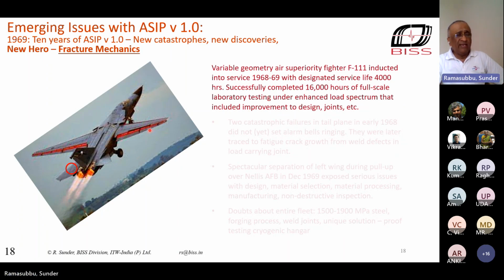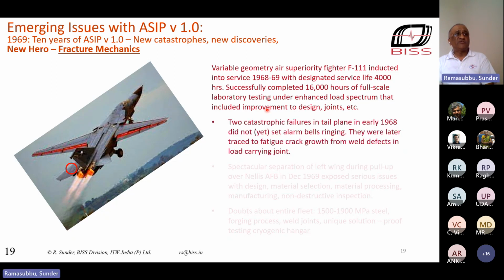So in accordance with the ASIP version 1, it was full-scale fatigue tested. It showed a life of 16,000 hours. They divided it by 4 and said, okay, you can use it for 4,000 hours. Now, very early in service, there were 2 catastrophic failures in the tailplane. But unfortunately, they didn't set alarm bells ringing yet. They were later traced to fatigue crack growth from weld defects in a high-strength steel load-carrying joint in the tailplane.